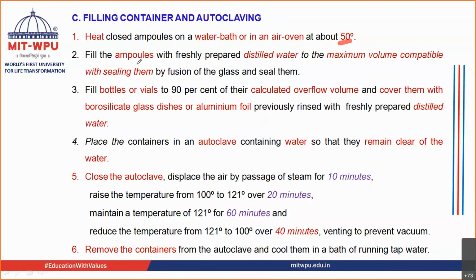Then what you are going to do is you are now going to fill the ampoule. If it is filling of an ampoule, then the quantity that you are going to fill with distilled water is near about the maximum volume that allows it to be easily sealed. Because I have told you that if you are sealing the ampoule and it is wet at the brim, at the top, at the tip, then the ampoule cracks, isn't it? So whatever the volume you can fill, you are going to fill it up to that volume.